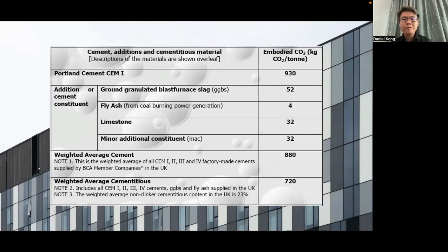But the problem with the blended cements approach is that cement still has a large contribution, or rather a large embodied energy. As you can see from this particular table here, cement does make up a large amount. And even if you have a small additive, it's not going to do enough to rid of this amount of embodied CO2. But of course, if we are to replace this amount altogether, this is where the beauty comes in, and that's the hope of really tremendously reducing this impact.